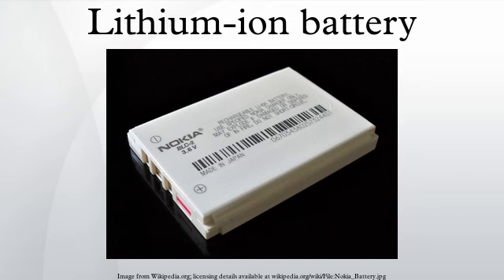In a lithium-ion battery, the lithium ions are transported to and from the positive or negative electrodes by oxidizing the transition metal, cobalt, in Li(1-x)CoO2 from Co3+ to Co4+ during charge, and reduced from Co4+ to Co3+ during discharge. The cobalt electrode reaction is only reversible for x less than 0.5, limiting the depth of discharge allowable. This chemistry was used in the Li-ion cells developed by Sony in 1990.